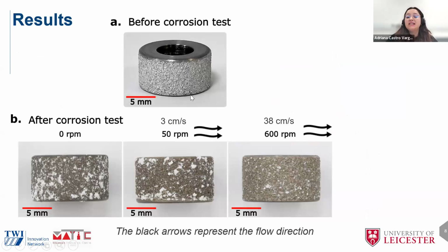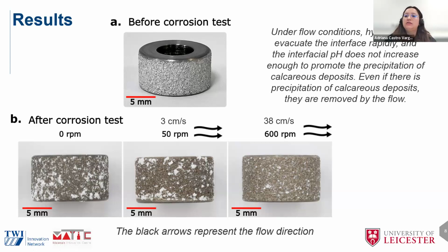As a result, this is the aspect of the coupons before and after exposure. The black arrows indicate the direction of the flow. We can observe that the coupons don't have any signs of rust or corrosion damage of the substrate. However, we can see that white corrosion products appear on the surface, and they decrease when we have high velocities. Under flow conditions, the hydroxide ions can evacuate the interface rapidly, and the interfacial pH doesn't increase enough to promote the precipitation of these calcareous deposits, or even if there is any precipitation of them, they can be removed by the flow. Naturally, it will have an impact on the kinetics and degradation of these coatings.